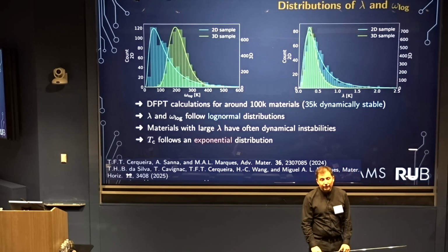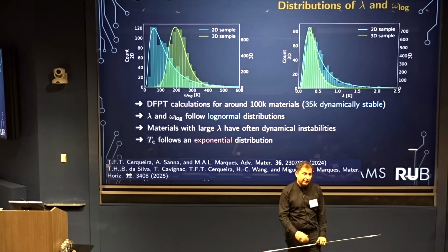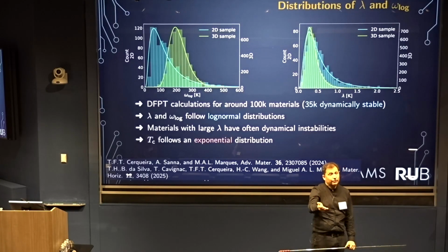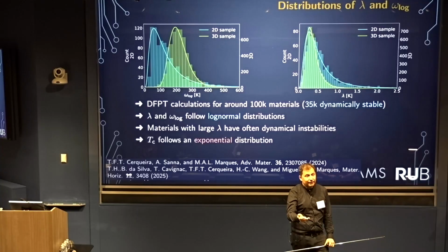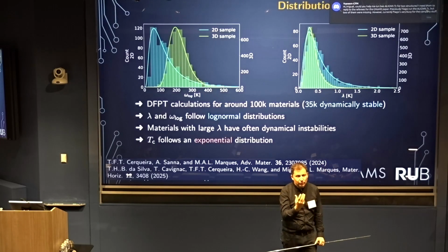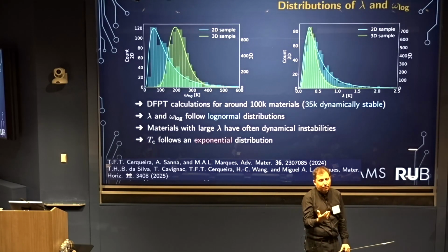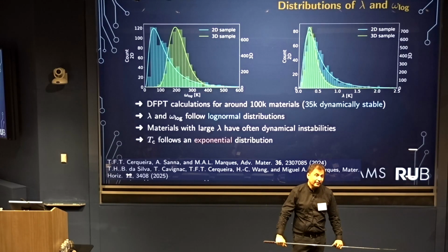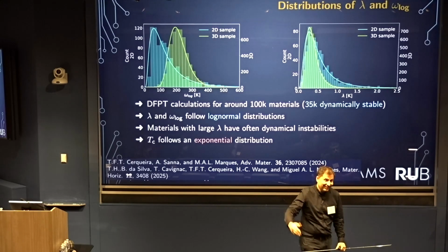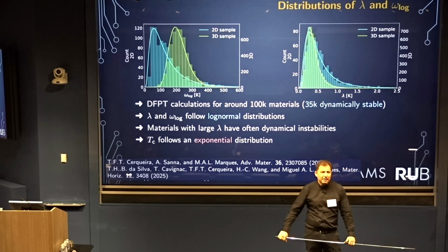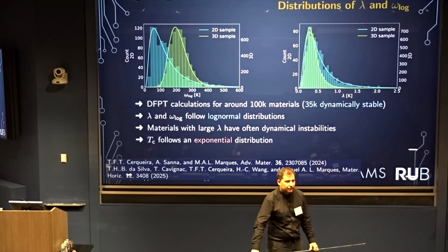Then I can also tell you that many of the compounds that are in the experimental database have antisites, disorder, vacancies, off-stoichiometries, and the TC that you have experimentally, I mean, the material science is complicated, right? And sometimes you have to take into account all those things to get the proper TC. So it is hard. Eventually, someone should go through that. Yeah, but it's again humanly time-consuming. You will easily spend months per compound sometimes.